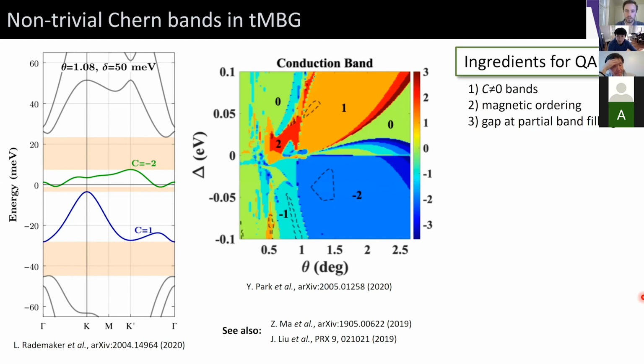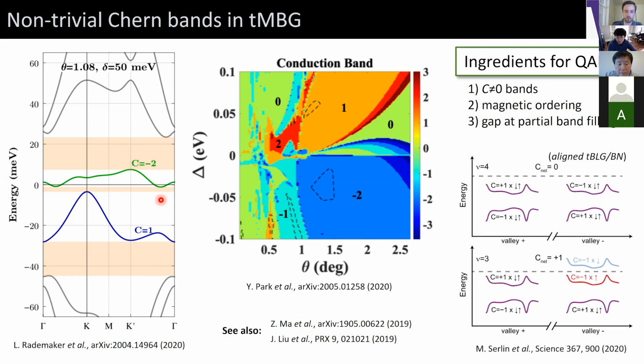Now, the ingredients for realizing a quantum anomalous Hall effect are that you have non-zero Chern bands, which is trivially satisfied in this system, but also that you have some sort of spontaneous magnetic ordering, and that you can actually realize a gap at partial band filling to polarize into just a single spin or valley sector, such that you don't average out the Chern number to zero when you fill all four bands simultaneously. And this has been done before in a number of different Moiré van der Waals heterostructures.